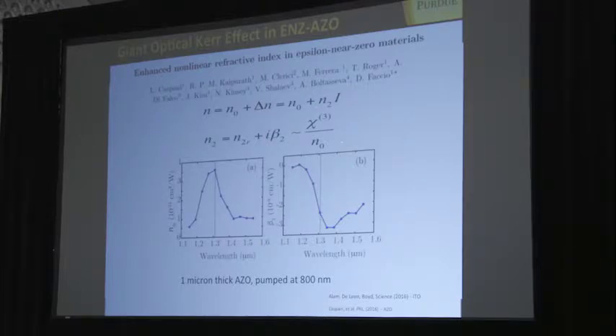But more than that, you have this linear refractive index in the denominator. Therefore, when you look at the nonlinear response as a function of wavelength, the closer you get to the point where epsilon goes to zero, the larger n2. And that's what we measured. You see it has a clear peak here at the point where epsilon goes to zero, therefore the refractive index becomes smaller and smaller. And this is just beta two.